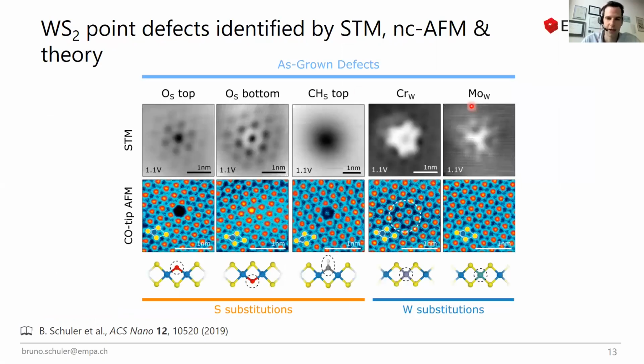Now that's again the kind of overview of the things we see in just as-grown tungsten disulfide. So in the first row, you see an STM image of individual defects here at positive bias. That means the empty states close to the conduction band. And here on the bottom part of the very same defect, in a CO-tip AFM image, you can essentially see the sulfur atoms in the top layer. So these are these red guys, but we also know the location of the tungsten atoms because in one of the sites, this looks a bit darker. So we know that this is actually the place of the tungsten. So from this, we know which site these defects are sitting.